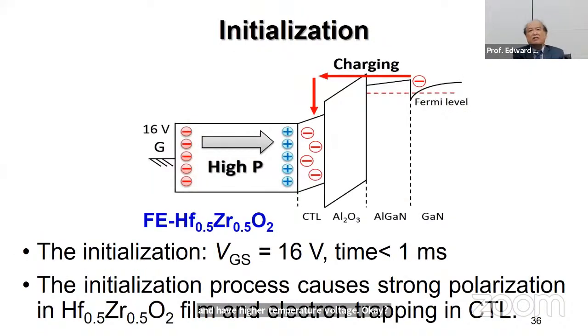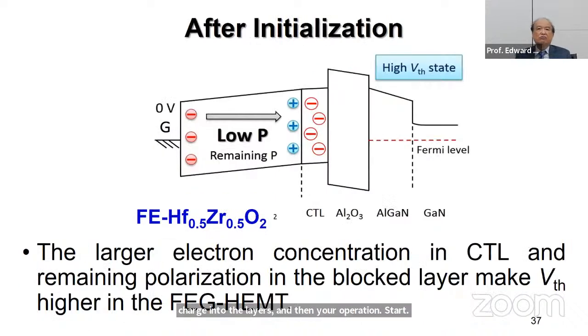And this kind of device needs initiation. So you apply 16 volts for less than 1 millisecond, then you initiate the process by introducing charge into the charge trapping layers, and then your operation starts to happen. And this is after initiation. You have a large number of electrons in the charge trapping layer, and your polarization starts to form, and that will give you the electric field that is against the voltage you apply to it.